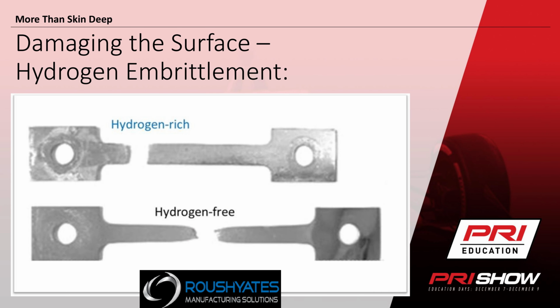Working with Roush Yates, sometimes they get environments where coatings can have a lot of hydrogen in them. When you get hydrogen into it, the hydrogen, like nitrogen, can make the surface actually stronger, but it also makes it brittle like glass. So these coupons, when they did one type of coating and tried to pull it apart, you can see how it didn't stretch at all.